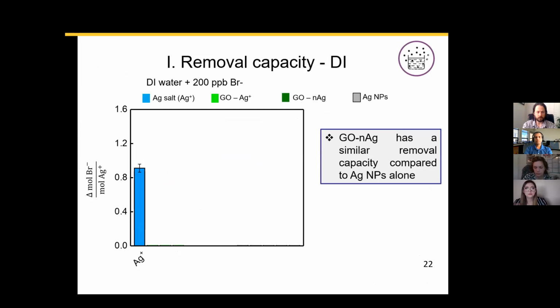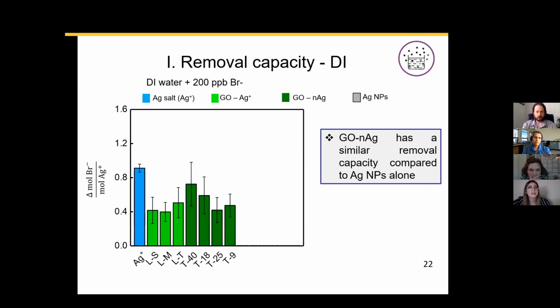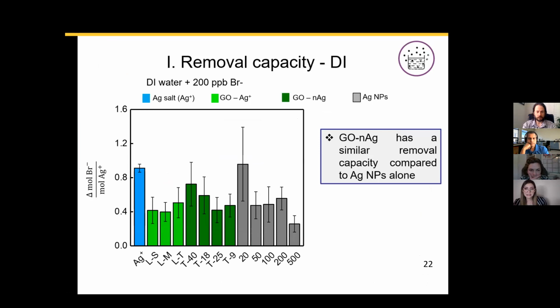So when we look at the first set of results, looking at just model water, with no competing ions present, we see that silver salt has a very high efficiency at removing bromide from water. When we start looking at our different composites, let's look at our silver salt composite. We see that that efficiency reduces, but when we look at the nanocomposite and the silver nanoparticles, we see that that efficiency actually is increasing. And if you look at the silver nanoparticles, we actually see a size-dependent effect, where the smallest particle has the highest bromide removal capacity, and the largest particle has the least.